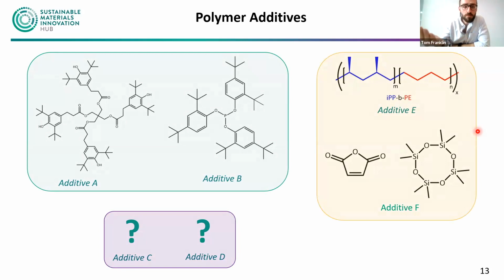So if you remember, I said polypropylene is quite a significant contamination issue. Well, these effectively help to stitch together. You end up with a polypropylene phase and a polyethylene phase. They don't mix, they refuse to mix. So you effectively have compatibilizers kind of acting as a zip. They stitch those 2 phases together and really help to minimize the effects that polypropylene has on mechanical properties. So 3 broad classes. As I said, this is not an exhaustive list of all the additives possible, but just a way of scoping out some different possibilities.